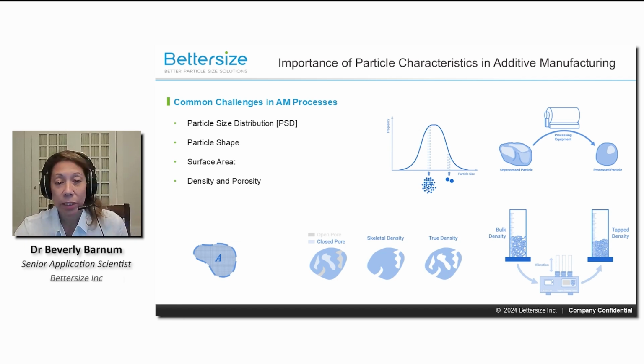So bulk and tap densities of powders determine how well they can be packed during the additive manufacturing processes. And the porosity of a powder is the ratio of the volume of voids in the powder to its bulk volume. And the porosity of the powder may result in internal defects in the final part in additive manufacturing.